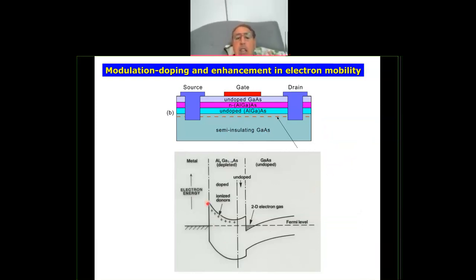So here, this is the energy profile. So the positively charged ions stay in the AlGaAs, and the electrons actually move to this interface. Of course, they cannot go deeper, because you got positive charge and, of course, a Coulombic attraction. So they only stay near the interface. This is what we call a two-dimensional electron gas. So they are only on the plane near the interface. So here, that's what they call two-dimensional electron gas. So they are in the interface between the AlGaAs and gallium arsenide. So that's extremely important.